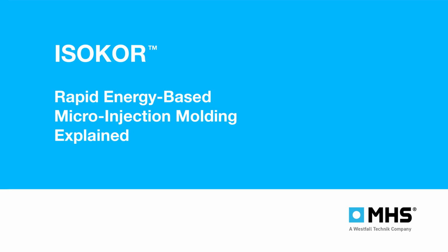Okay. When you combine that tight geometry with the explosive expansion pressure, it subjects the melt to an incredibly high shear rate for just a tiny fraction of a millisecond. In polymer physics, this induces shear thinning. Right, shear thinning. The high friction forces the molecules to align perfectly, drastically dropping the viscosity. The shear thinning effect makes it suddenly become as thin and runny as water right as it hits the gate. Exactly. So it explodes into the cavity at maximum speed with minimum viscosity, effortlessly filling the microscopic features before a frozen skin layer can even begin to form on the cavity walls.